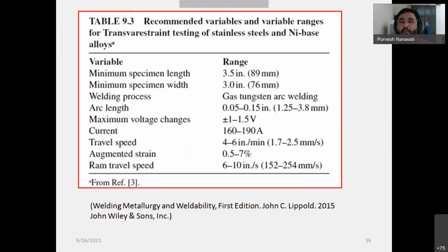Now, from the same book, I have captured a table, and these are showing different welding variables to perform this test. Okay, you could see the specimen length in mm is 89 mm. Specimen width is 76 mm. Process is GTAW. Arc length is 1.25 to 3.8 mm. Hope you understand by the arc length, right? It is the distance from the tungsten electrode tip to the workpiece.